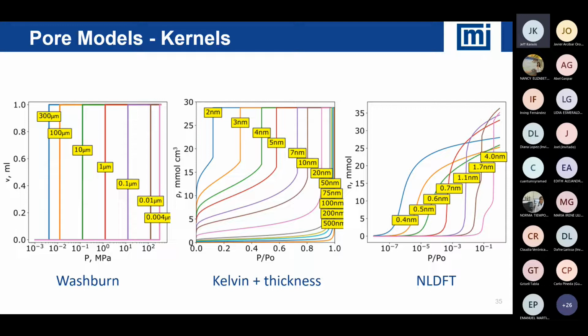So three really differences associated with it. Notice on the right side, each isotherm does have some different behavior associated with it. And modern techniques, especially when you look at the pore being saturated. So look at the highest pressures from NLDFT. Notice different sizes have different quantities adsorbed. Compare that to the center BJH. Notice it doesn't matter what size you look at for BJH, they all go to the same quantity in the pore. That's the liquid density. Okay, so NLDFT, more precise, more realistic with the quantity in the pore versus using some of the classic techniques.